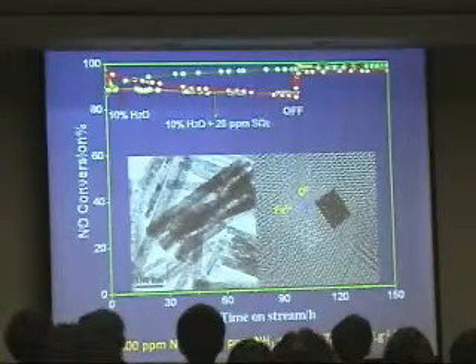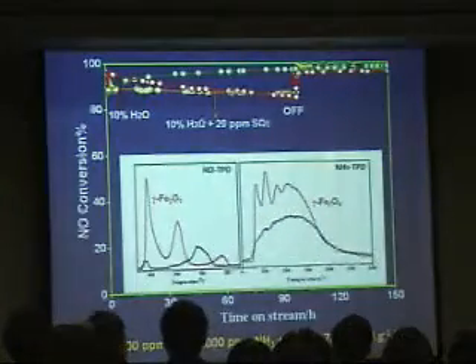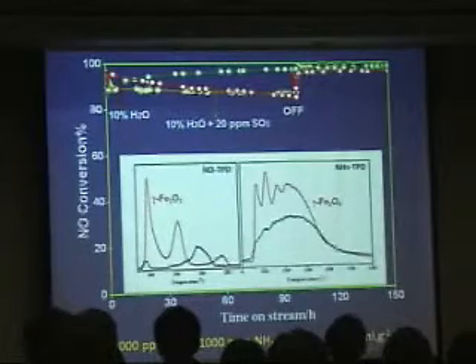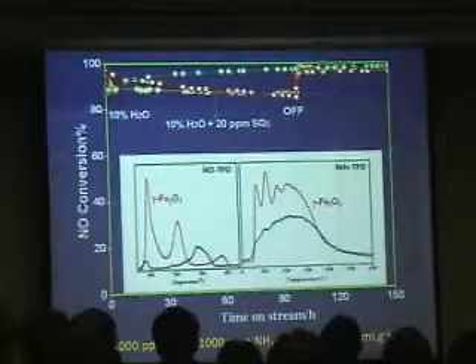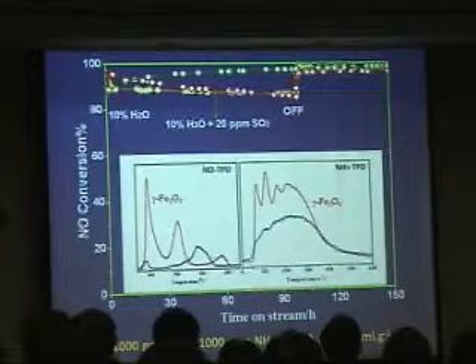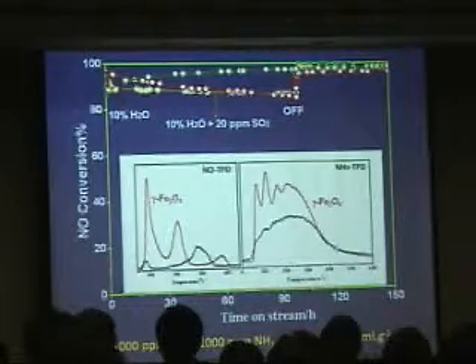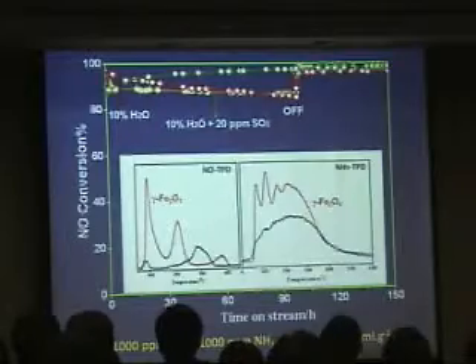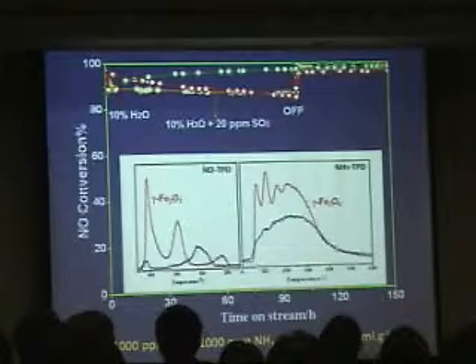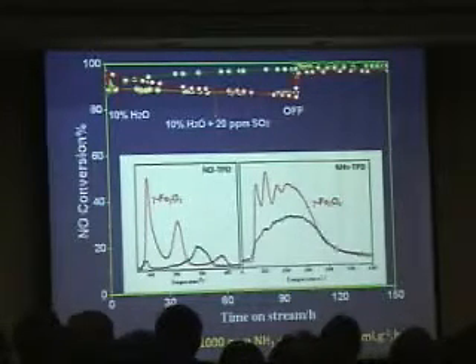So the performance of this iron oxide still comes from the morphology effect. Because they can partially expose the iron species on the surface, it enhanced the adsorption of two important reactants. One is ammonia, another is NO. If we compare with conventional iron oxide, the adsorption of these two reactants was largely increased. That's why they showed very high activity for this DeNOx process.